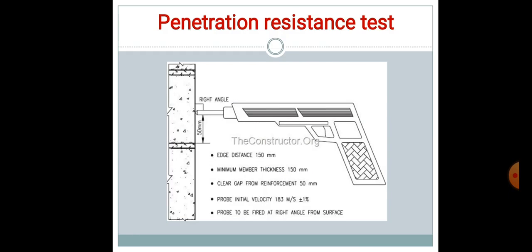How does it work? This test can be done in 5 steps. Step 1. Provide a minimum 150 mm edge distance from the surface of the member. Step 2. The minimum thickness required for the member is 150 mm. Step 3. Leave a 50 mm clear gap from the reinforcement present in the member, since the presence of reinforcing bar within the zone affects the result. Step 4. Provide an initial velocity of 183 meters per second to the probe, with a 1% difference allowable in the velocity. Step 5. The probe is to be fired at right angles to the surface.